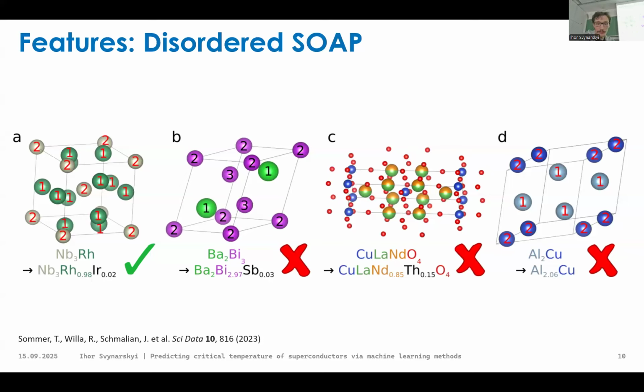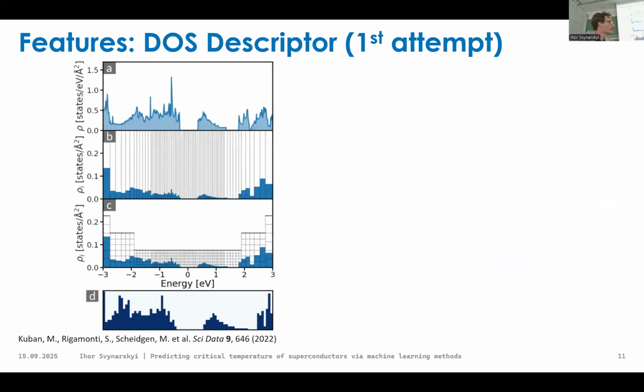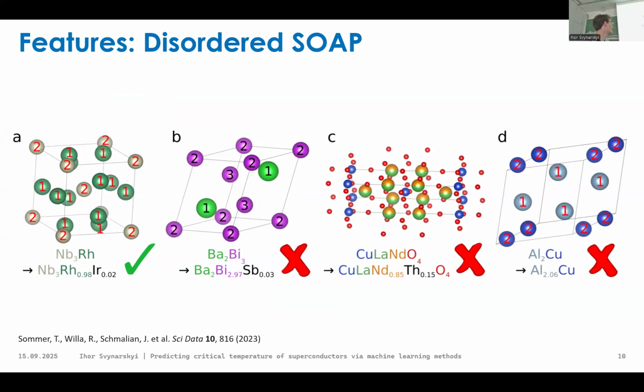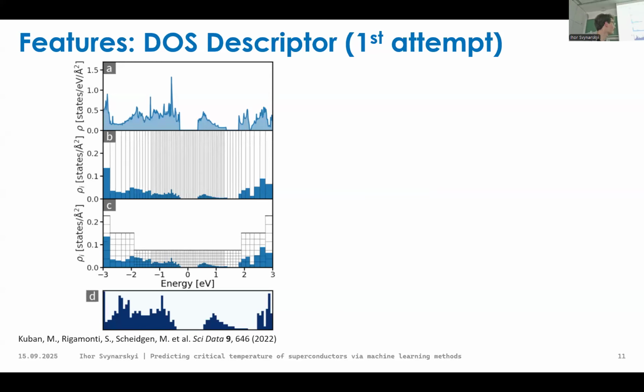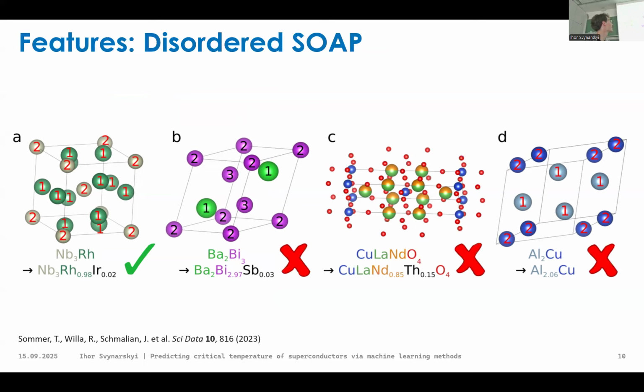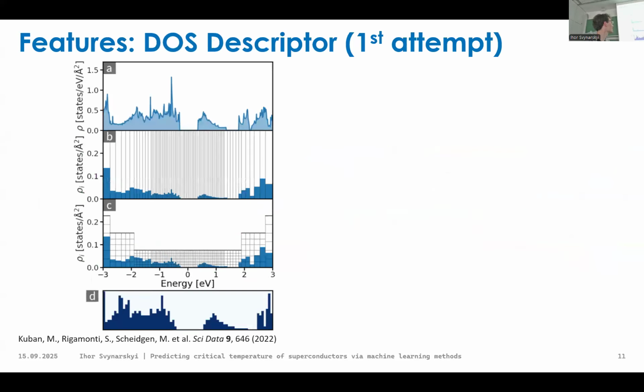And as I said before, we also try to add some of those descriptors because we would like to see if it could make our predictions better. So for each compound, we have, let's say, a Materials Project parent, even if it's a doped structure, but we could assign some similar structure as its parent, and then use the density of electronic states of this structure basically as those of this one. So it's not really good, but with this disordered SOAP accounting for this doping, it's worth trying to do this.